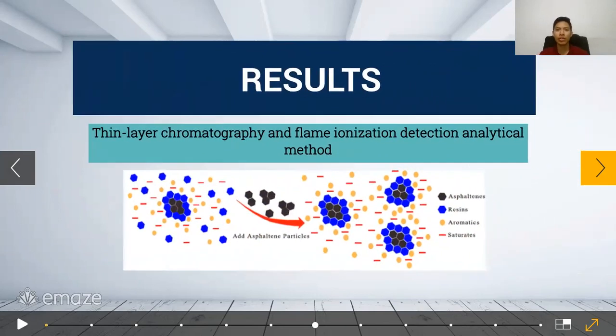The experimental section consisted of analyzing 5 samples of crude oil using a method called thin layer chromatography and flame ionization detection. This analytical method is used to provide a more reliable way to obtain the SARA components. The apparatus process in summary consists of the oxygen and hydrogen flow rate ratio, which influences the stability of the test results and causes a deviation, so it shows the fraction of the SARA components.